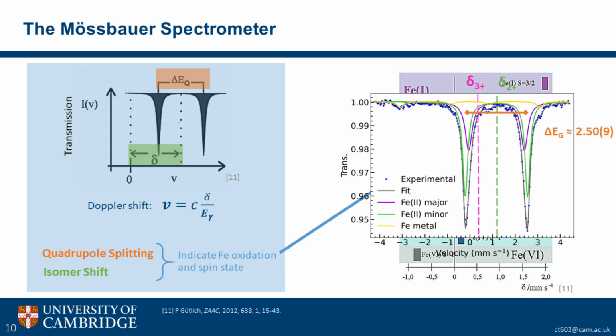The quadrupole splitting, which is the distance between the two doublet peaks, and the isomer shift, which is the distance of the center of the two peaks from the zero velocity. And by looking at the combination of these two values, we're able to really clearly pinpoint the iron oxidation and spin state when it's inside our sample. So this is a map that shows all the different combinations and how we associate them to different